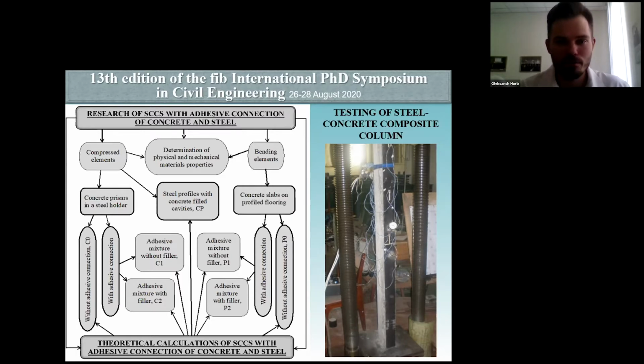documents, we talk about ensuring work of steel and concrete on every stage of loading, but we can't describe third layer in this construction as polymer, because polymer adhesive we can put in this construction getting some thickness over this. It can be 3 millimeters or 5 millimeters, or in some constructions we tried, we put more than 10 millimeters, and it's very important to joint work over two different types of materials, steel and concrete.